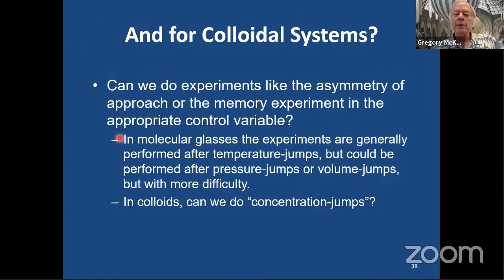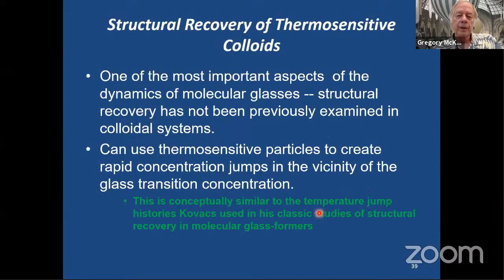So can we do experiments like the asymmetry approach or the memory experiment with the appropriate control variable? In molecular glasses, the experiments are generally performed after temperature jumps, but in principle, they could be performed after pressure jumps or volume jumps. But of course, experimentally, those are much more difficult. In colloids, can we do concentration jumps?